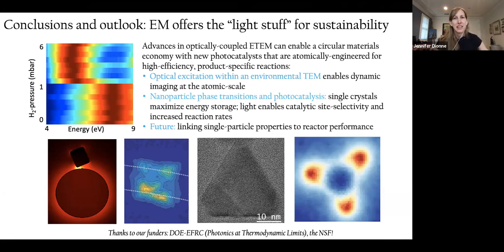So I shared with you how we can enable optical excitation within an environmental TEM for dynamic imaging of reactions at the atomic scale, and now with atomic scale resolution, thanks to direct electron detection. And then I also shared with you what we've learned about nanoparticle phase transformations and light-driven phase transformations. These single crystalline nanoparticles maximize energy storage, so they only exist in one phase in thermodynamic equilibrium compared to the polycrystalline nanoparticles. And then light enables significantly increased reaction rates, as well as catalytic site selectivity and the opportunity for favorable intermediate states.